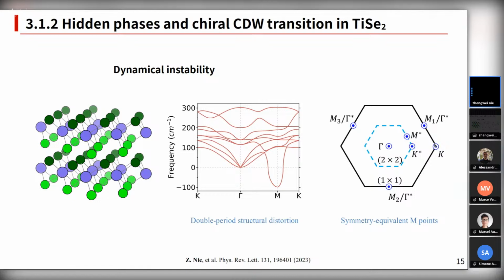Due to its rotational symmetry, the soft mode has an imaginary frequency, its energy is negative, so if the structure is distorted along this direction it will be stabilized. So its initial structure is not stable.